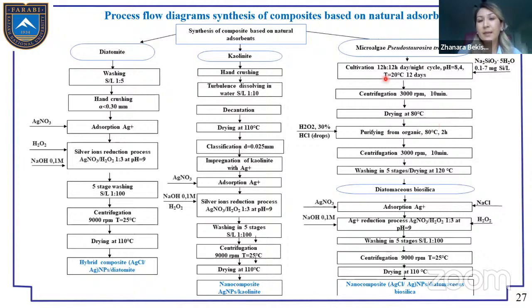And the next process flow is obtaining the hybrid composite based on diatomaceous biosilica with silver chloride and metallic silver nanoparticles, with cultivation, purification, centrifugation of microalgae, and obtaining the diatomaceous biosilica, and the stage of obtaining the nanocomposite with adsorption and reduction, and washing of the obtained composite, drying.